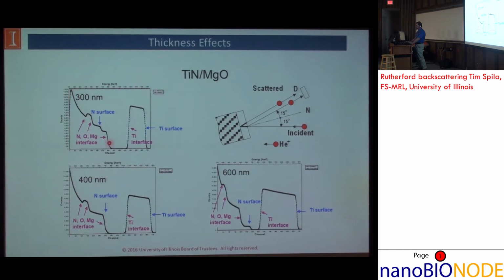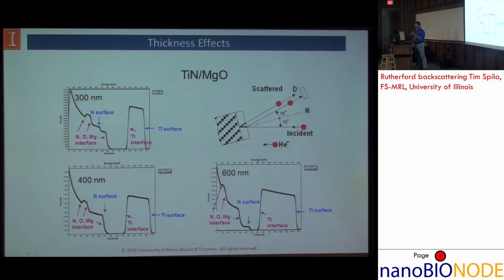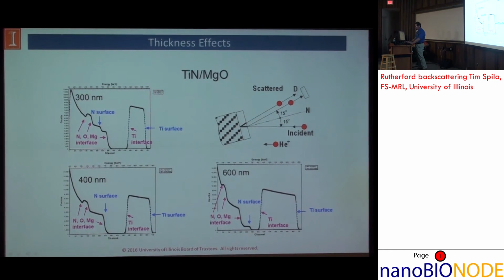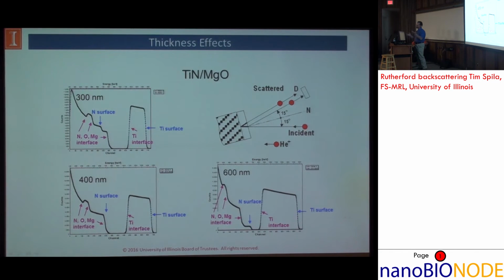So here's the magnesium. If you get at the right thickness, you can actually be in a situation where the nitrogen from the surface and the magnesium from the interface are at the same energy, and so it causes some questions, you're not sure about it. Of course, if you grow thicker, then the nitrogen at the surface doesn't move, but the substrate moves, and so the magnesium moves further in, and so now you don't have that problem anymore.